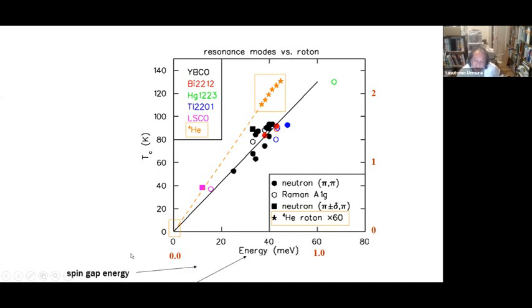And moreover, as you know, this resonance mode has an hourglass shape. What is important here is the smallest energy excitable mode, and that is called the spin gap in the case of cuprates. If you plot the spin gap energy and the onset temperature Tc, then the ratio is almost exactly the same as that of the rotons.